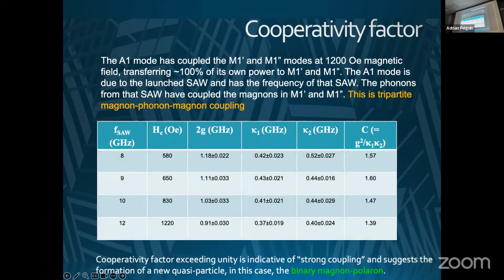So you need to have what we call phase matching to get strong coupling. The frequency has to match, and in this case, the frequency matches. We can actually engineer this because the magnon frequency is a Kittel mode, so it can be changed with the magnetic field. So we picked the magnetic field and the array parameters judiciously here, such that the frequencies of the two magnon modes and the phonon mode match. All three of the frequencies match, and that's why we can do this. So there's some engineering involved here.